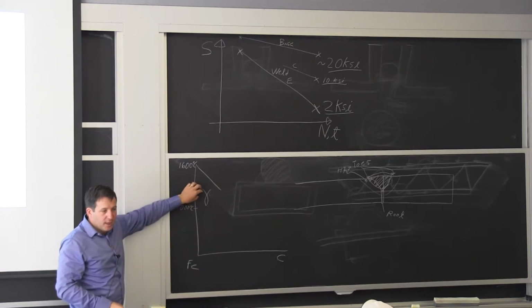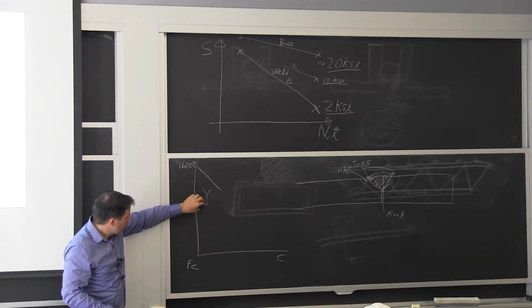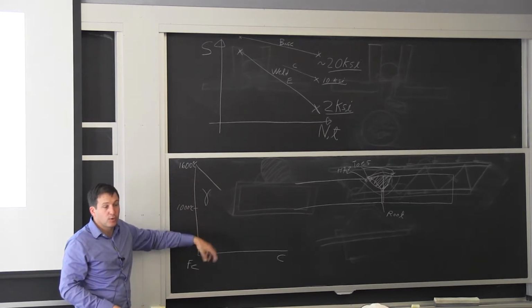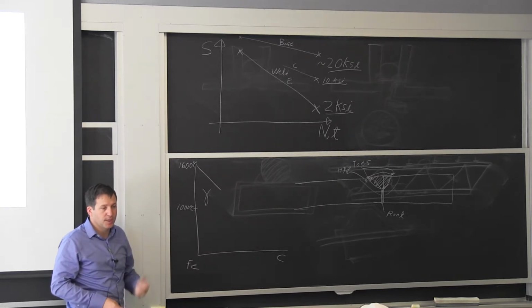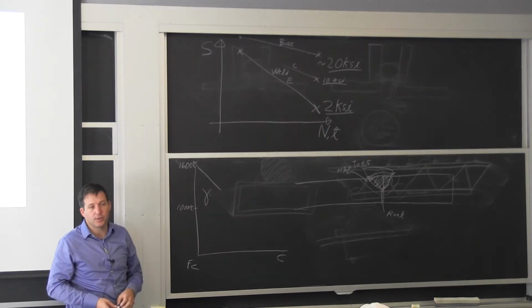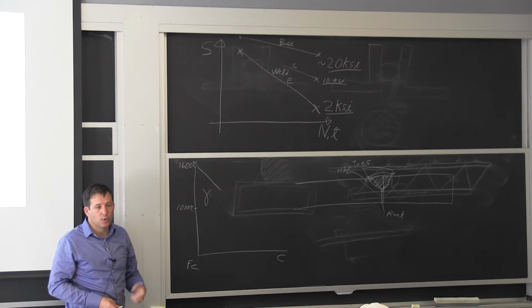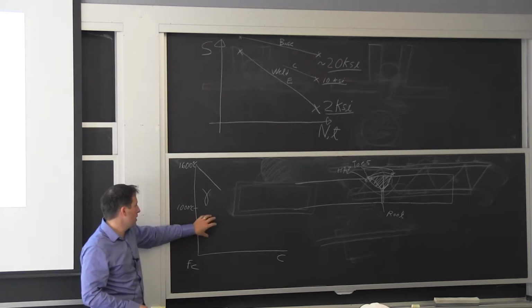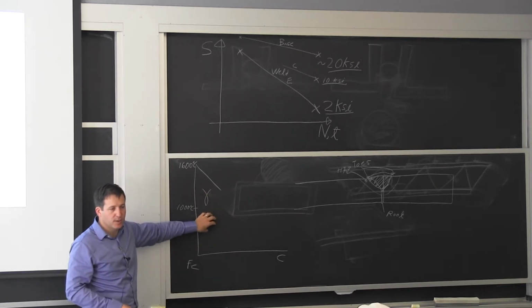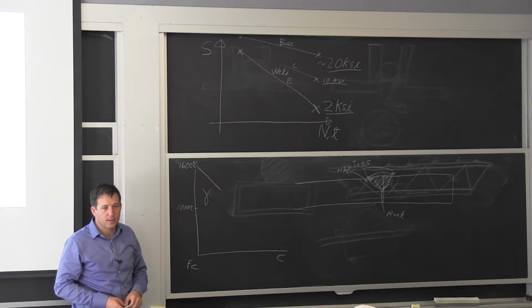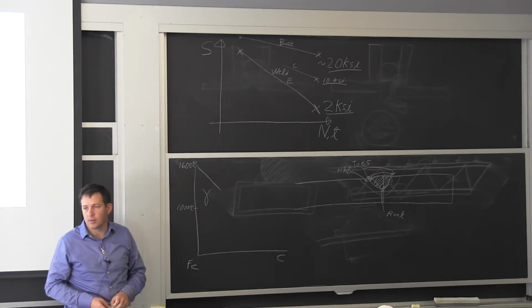When you form that austenite and you further cool down is where you go back to all these transformations that we talked about. So the main idea is you went back to austenite here, and then your cooling rate is going to determine if you're getting the equilibrium phases from it or if you're getting the martensite. And that's where it's dependent on the alloy.